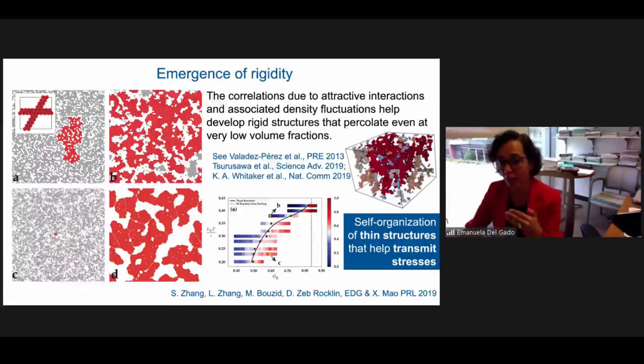And this is in fact what we see in these colloidal gels, and also more widely in particulate gels: I can get a solid response with a relatively tiny amount of solid material. Of course, this is hard to see in experiment, because if I look at the structure, how would I recognize this essential rigid structure that is growing in the system? There are a lot of other processes going on that do not necessarily bring in the important connections, and they do not necessarily contribute to the localized stress pattern that I would like to see. But indeed, in the last few years, there have been a couple of experimental studies, and experiments combined with simulation, combining imaging and rheology, that have seen elements consistent with the scenarios that we've described here.